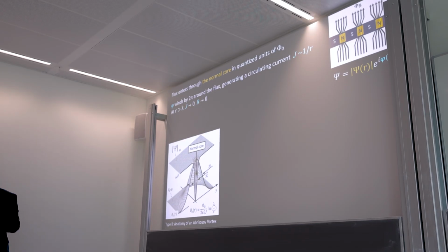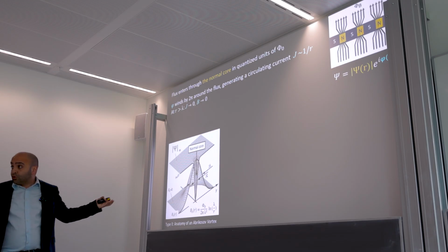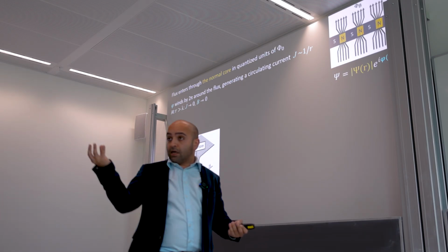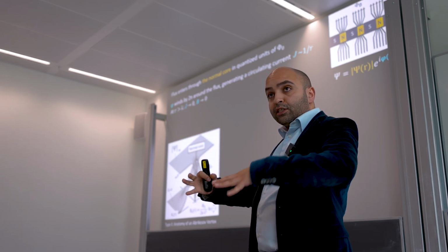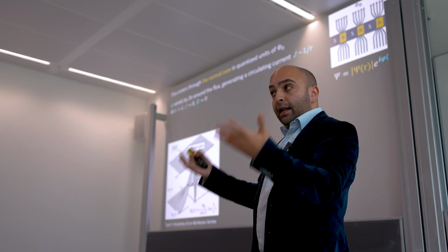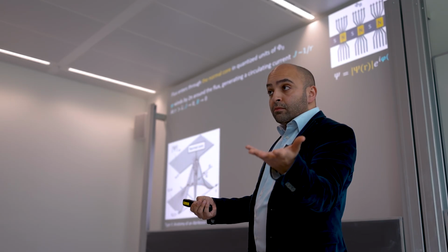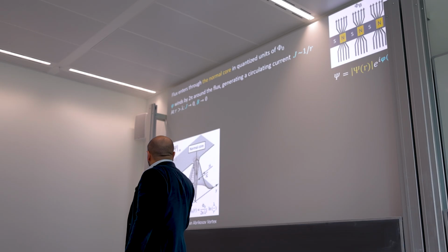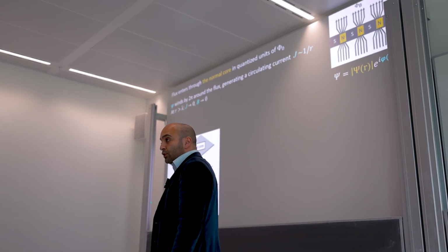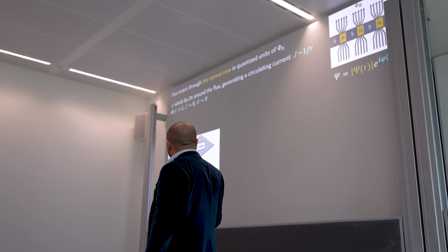And if you think about it, the two length scales are very clear in what they do here. The normal core, what's the diameter of the normal core? It's the coherence length. The diameter is 2 coherence lengths. That's the size of the vortex core. But there's a field around it. Of course, the field needs to be screened by the current. And the characteristic length for that is? Thank you. It's lambda. So far away from the core, there is no field. And as you get closer and closer, you have the field, and this is the relation.